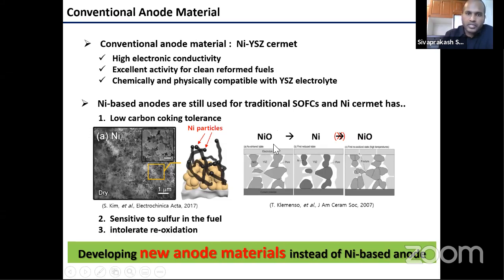So if you use nickel as an anode material, we have to continuously keep running the fuel cell. Even when we decide to stop it, we cannot, otherwise the cell will break. So when we start using the alternative fuel cell, the direct hydrocarbon fuel cell anode where nickel is not present, we use a different electrode material, where upon fuel depletion we can stop the fuel cell and then start running it again.